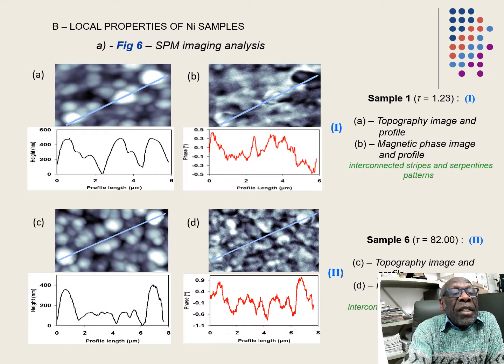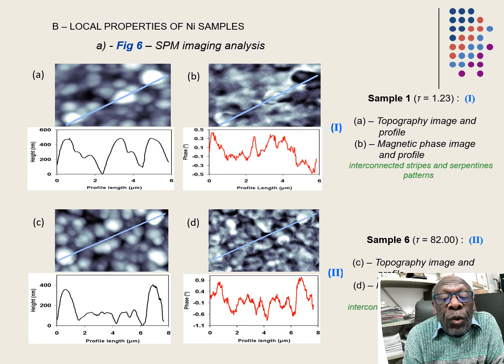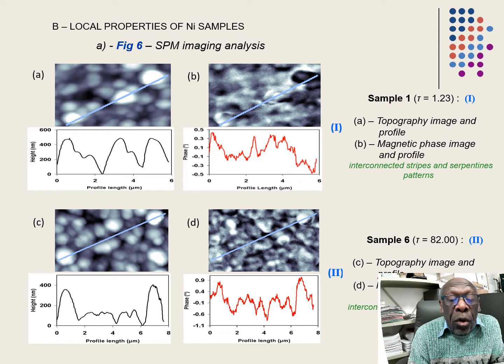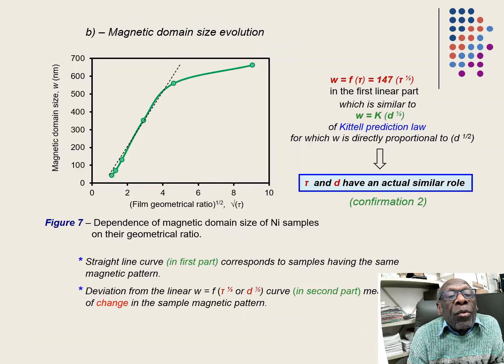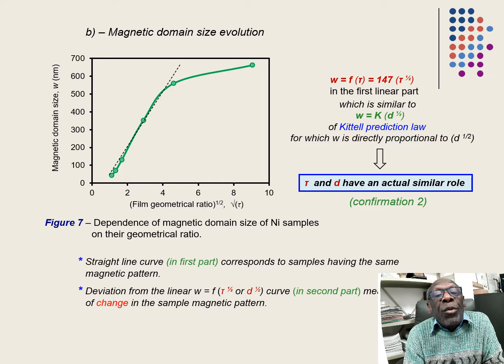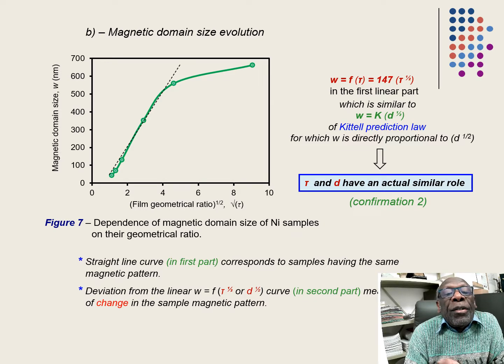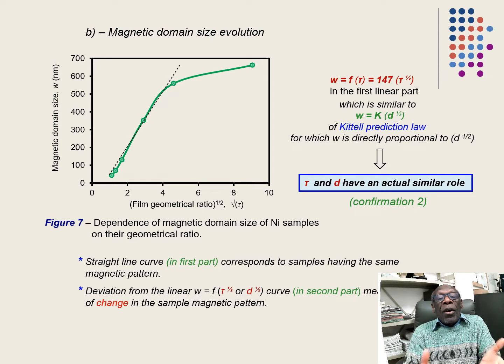Here, more important is the magnetic phase image given here that will allow the determination of the local magnetic properties. An example of local magnetic property is here, magnetic domain size. We can follow here the evolution of this property versus tau. In red is the expression corresponding to the result, which is here exactly similar to the result of the Kittel prediction law, when d is used in place of tau, which is the second confirmation of the similar role of both characteristics.